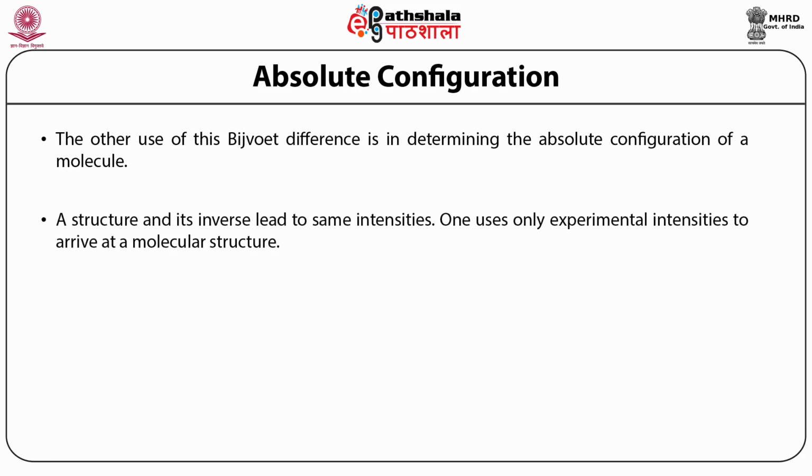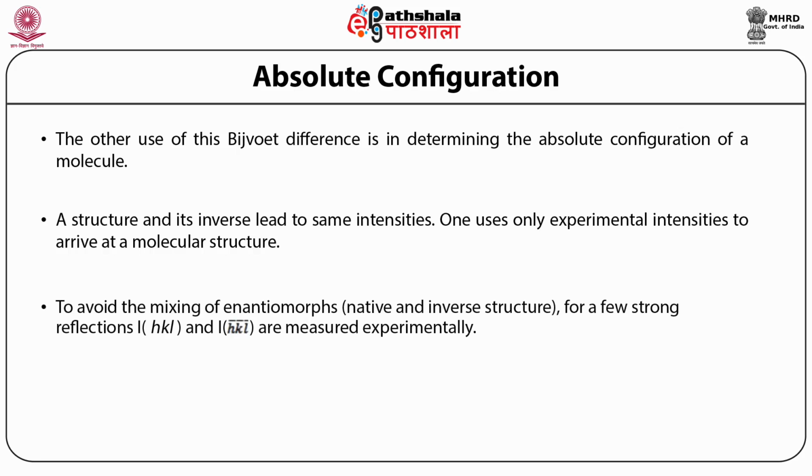A structure and its inverse, if you call the structure S, its inverse is S bar, they lead to the same intensities. One uses only experimental intensities to arrive at a molecular structure. To avoid the mixing of the native and inverse structure, for a few strong reflections, the intensity of HKL and the intensity of H bar, K bar, L bar are measured experimentally during the data collection.